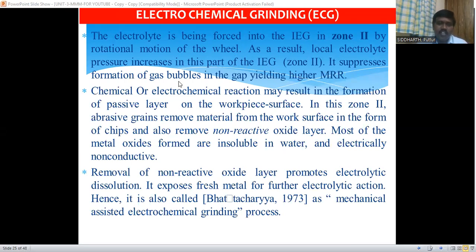In zone 1, what we discussed, because of the chemical reaction, some gases will be developed, and because of those gases, the conductivity will be reduced. But in case of zone 2, because of the pressure, the gas bubbles will be reduced, so that it suppresses the formation of the gas bubbles, and finally it is going to yield a higher MRR, means metal removal rate. It increases the metal removal rate.